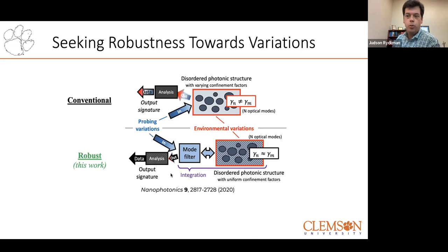So we said, let's back up and just use integration to our advantage. Using our on-chip grating couplers and single mode waveguides, we can filter out a lot of the probing variation. So if the optical fiber is twisted a little bit or misaligned, that issue is going to be filtered out because of our grating couplers and waveguides. And now the optical design is also done a little bit carefully. It's not too multi-mode. It's really mostly in these single mode waveguides where we can achieve a pretty uniform confinement factor, meaning all the modes in our structure will have a similar or almost the exact same thermo-optic sensitivity, and that will allow us to mitigate the temperature effects.